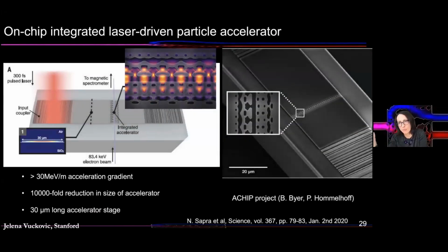So again, once you have the whole design, you can build the system. Here is the stage of the accelerator, which is 30 micrometers long. Here is the coupler, which is also designed in such a way that it can couple these energetic, very short pulses from the laser without damaging and burning the structure. And what you do in the actual system is you couple the laser, you propagate, you have the stage of the accelerator here, all in silicon, and you measure performance.